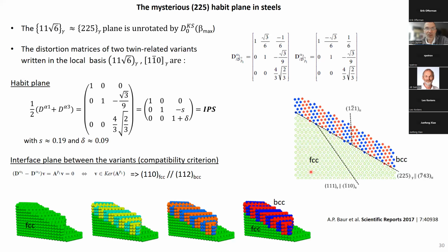Okay, what is nice also is that you realize that this plane here is unrotated by this distortion matrix. And not only is it unrotated, but if you combine two variants that have this plane unrotated and that also share a common direction, you can make an average of these two distortion variants and you get an IPS. So even PTMC promoters should be happy with that. And you can calculate what is the shear amplitude or what is the dilatation perpendicular to the shear. You can calculate also the interface between these two variants, and it is a 110 parallel to 112 of the martensite. And more or less, you can make a movie of the phase transformation with these two variants, and you have this schematic representation of what happens to go from FCC to BCC with an invariant plane here. It is not invariant by one distortion, but it is invariant by the linear combination of these two distortion variants here.